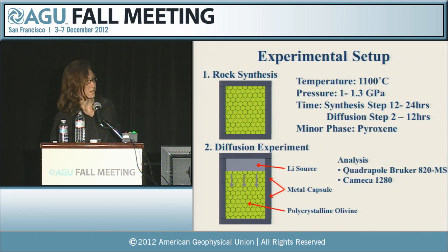So our experimental setup consists of 2 steps: a rock synthesis step, where powdered natural olivine or synthetic olivine is packed into either an iron or nickel capsule. That capsule is then run in a piston cylinder apparatus at 1100 degrees from 1 to 1.3 gigapascals for about 12 to 24 hours. And there's always a minor phase included, like pyroxene, which controls the grain size by grain boundary pinning.